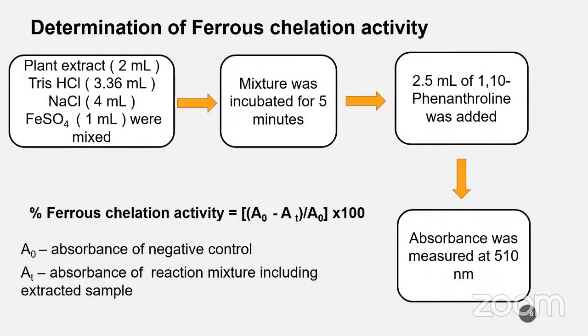Then we analyzed the ferrous chelation activity of the obtained extracts. First, plant extracts, Tris-HCl, sodium chloride, and ferrous sulfate were mixed, and that mixture was incubated for 5 minutes. After that, 1,10-phenanthroline was added as the indicator. Finally, absorbance was measured at 510 nanometers using that equation. The ferrous chelation activity was calculated as an inhibition percentage.